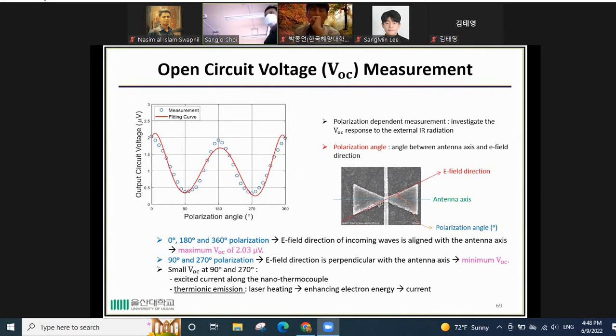And you can also see lower VOC occurs at 90 degree and 270 degree polarization. We can see from this 90 degree case and 270 degree case a small VOC because of the excited current along the nanothermocouple, and also because of the thermionic emission, because the laser heating can enhance the electron energy and then generates the currents over the nanothermocouple.